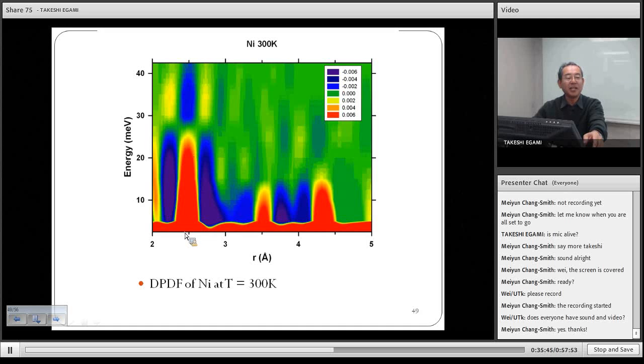So if you wanted to study propagating phonons, the regular S(Q, omega) analysis is better because it gives you dispersion, right? But if you wanted to study localized phonons, then this technique is better. So in perfectly crystalline materials, you don't need this. But in highly disordered systems, either crystalline or liquids and gases, this DPDF is very useful. And this is the case of lattice phonons, but it's useful for spins too. So this technique gives you the state of localized spin fluctuation. So we are planning to do such an experiment.